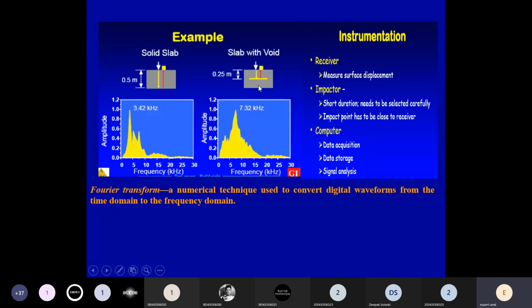Concrete pavements can also be checked using this equipment. For example, in the case of a national highway road, the thickness is 300 mm in the drawing. Is the similar thickness throughout the length or not? Any deviation in delta T, which is the transit time, if it is less, your frequency will be more. So higher frequency indicates some kind of issue. And once you see some issue, you can go for further investigation. This equipment is a bit sophisticated, but it is very, very useful when you have only one face available.